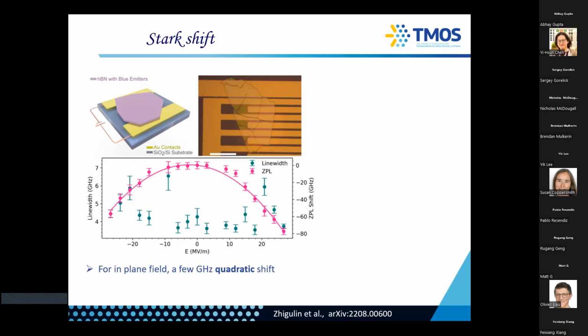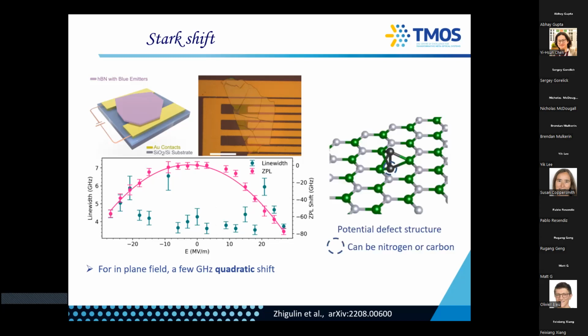So typically this type of behavior is limited to defects with inversion symmetry. With 2D systems, there's almost no inversion symmetry. You need a very specific configuration of your layers to get there. And so the idea is then that the defect is something that looks like an interstitial. An interstitial in this case is if you're taking an atom out and instead you're putting 2 atoms a little bit below and a little bit above. Okay, and this is what's called a split interstitial.